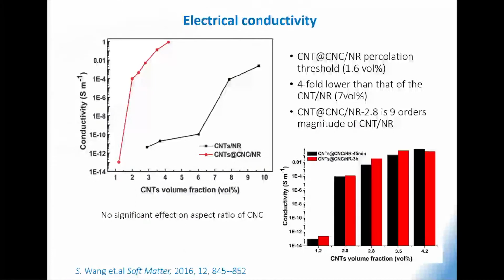You might ask, what is the advantage of this? If you put carbon nanotube into natural rubber, only natural rubber, no CNT. Only CNT. Look at this, this is CNT. CNT natural rubber. You get a percolation beyond 5.5 or 6 volume percent of CNT. Look at this. This is a percolation process. Natural rubber and CNT. CNT is very difficult to be dispersed in natural rubber.